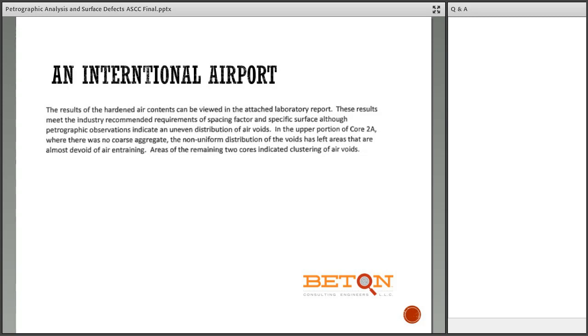The taxiway has a little bit of raveling going on some of the cracks. Talking to the contractor, it appears that there was a little bit of over-aggressive sawing. So it's a little bit of cracking perpendicular to the joints. The petrographer goes up, or rather somebody goes up and takes cores and sends them to the petrographer. And they look under the microscope and say, oh, look, it's air entrained, but the air voids are all non-uniformly distributed. This is a great, terrible thing.